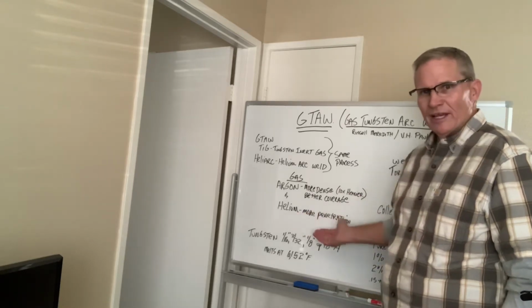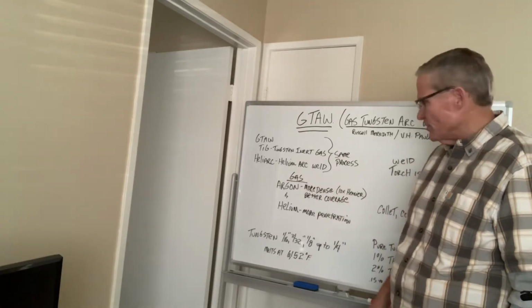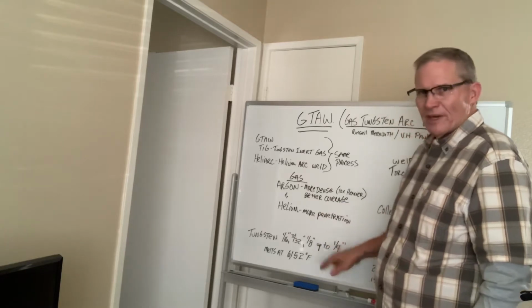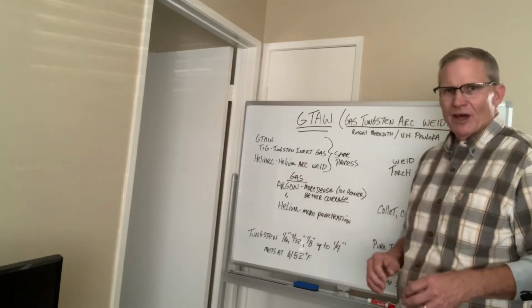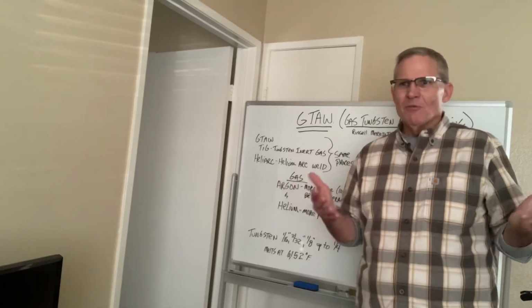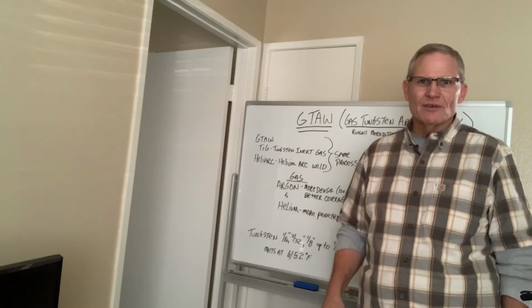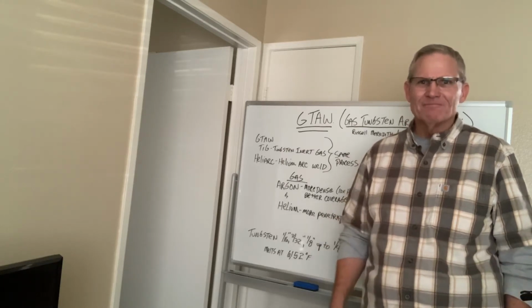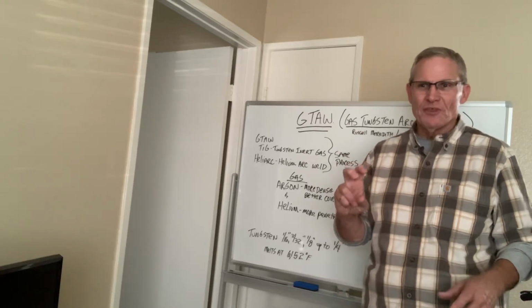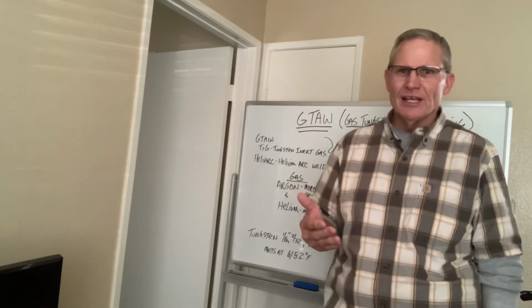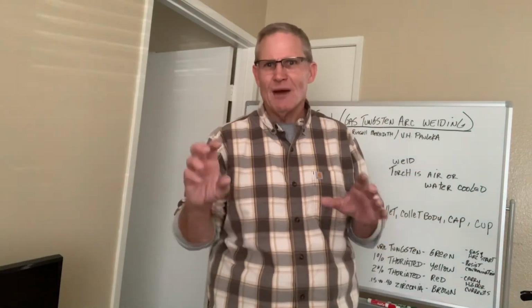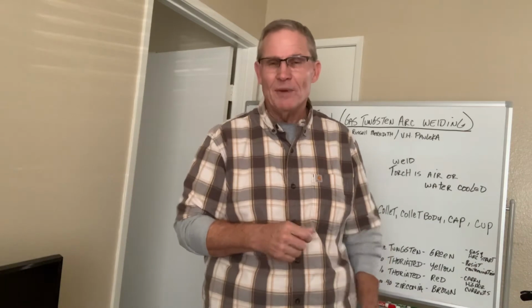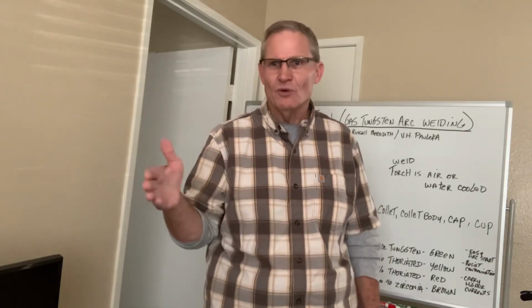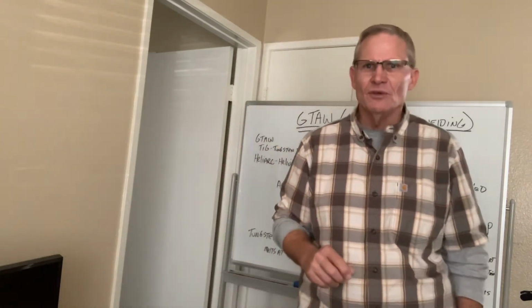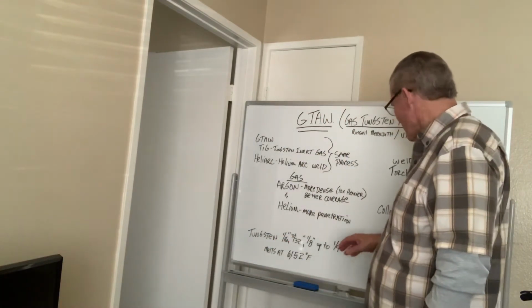You may be asking, well, why go to helium if it's that dense and it provides that well of coverage? And that's because helium gives you more penetration and allows you to penetrate on the thicker metals. You know, in my almost coming up on 40 years of welding, I've only used the helium gas once. I was welding a real thick piece of aluminum, and I used the helium gas. But that doesn't mean if you end up in a fab shop where there's a lot of thick aluminum, you would not be using quite a bit of helium, and also with other alloyed metals that you may be welding. It's when you get into the thicker metals that you introduce the helium gases.